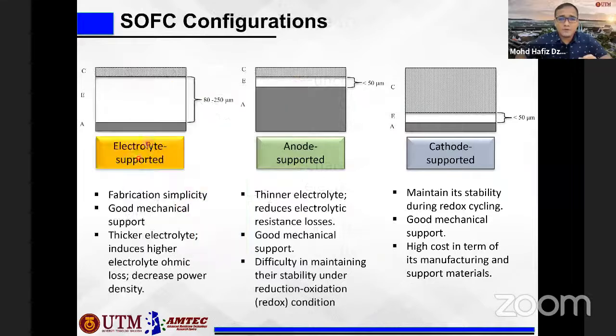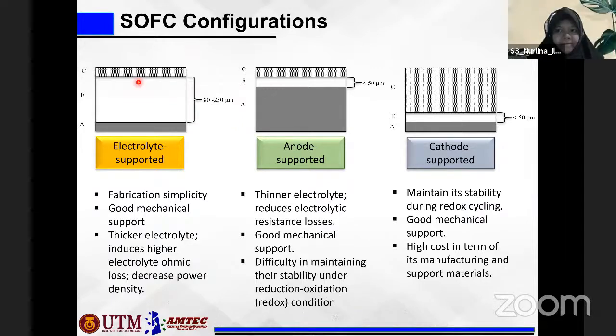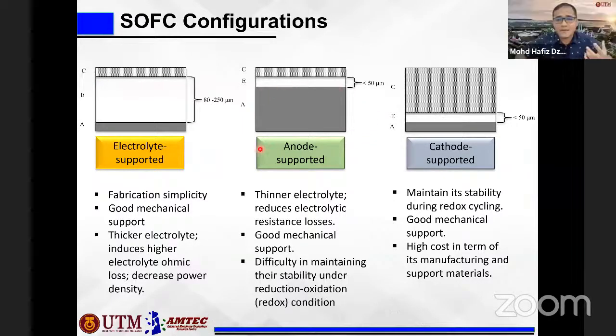So the normal configurations of solid oxide fuel cell: it can be found as electrolyte supported, meaning that the electrolyte is the thickest part, or it can be found as anode supported, meaning that the anode is the thickest one, or cathode supported, meaning that the cathode is the thickest part. But the most common configuration is the anode supported, because normally the anode material, nickel or nickel oxide as the precursor material for fabricating the anode, is the cheapest material compared to the material for the electrolyte and cathode.